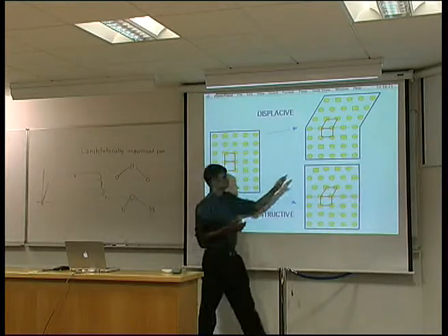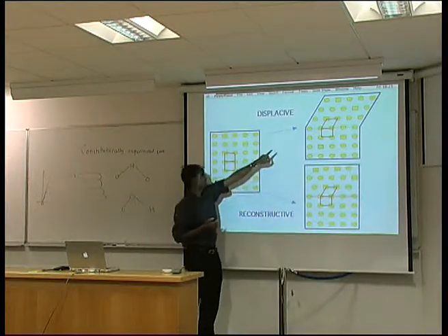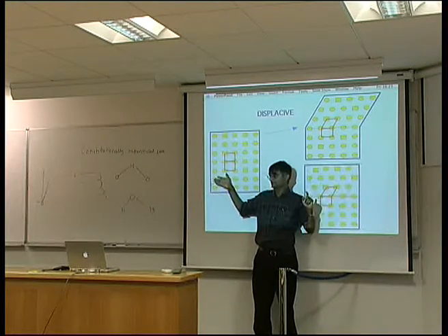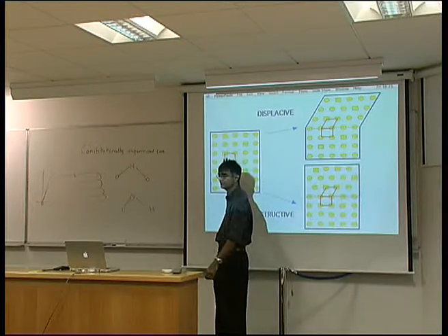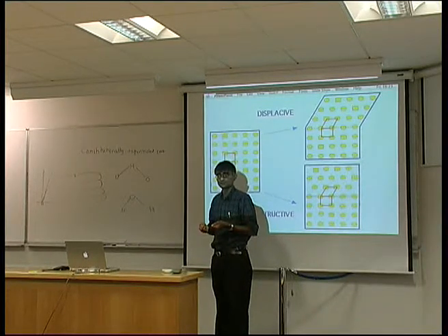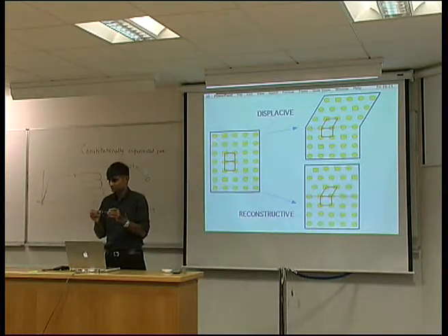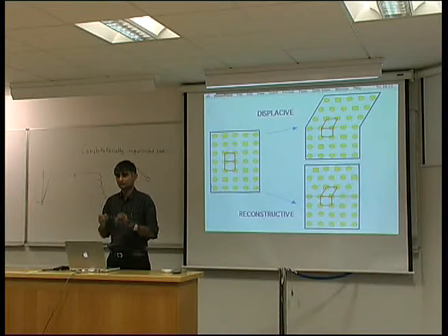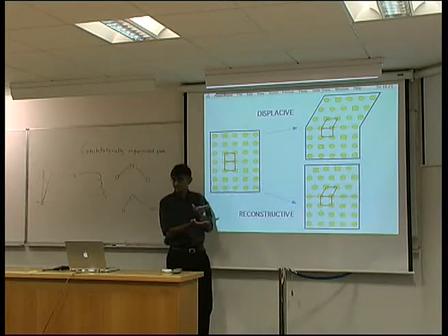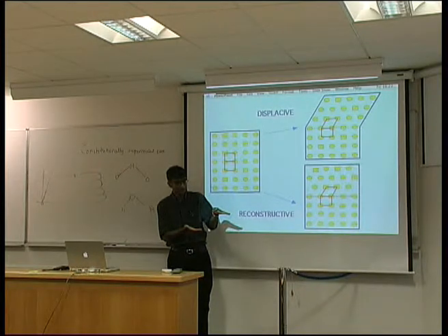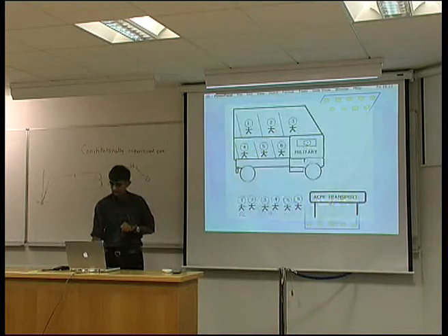And the other thing is that because there's no diffusion, there's no change in the neighbors of the atoms. So if you look over there, this sequence is exactly the same as this sequence. So it retains a memory of the arrangement of atoms in the parent phase, and if I reverse the transformation, I regain the original shape. Have you heard about shape memory metals? These are not shape memory glasses, but if they were, I could crush them and then put them in hot water and they would recover. You've heard about that, right? That's exactly this. So the mechanism of transformation involves a deformation of the lattice into a different structure. And if I reverse that by heating or whatever, then I recover the shape.